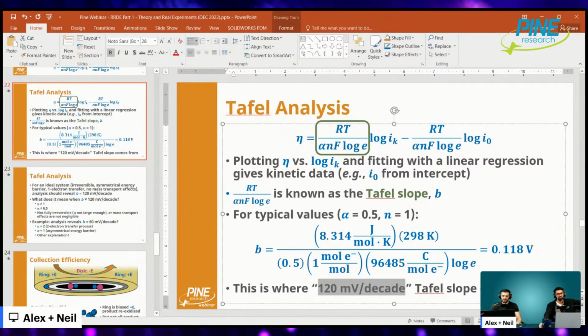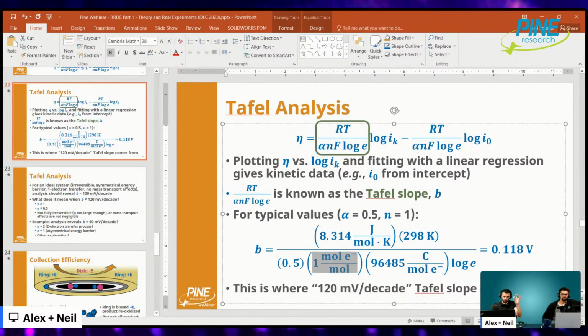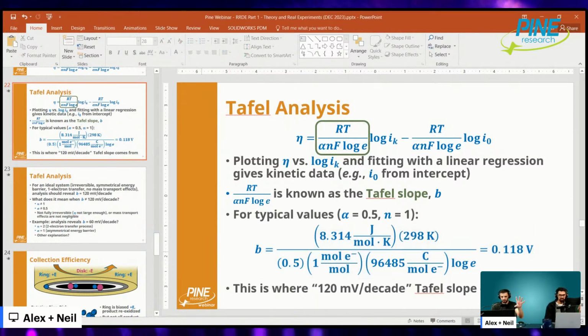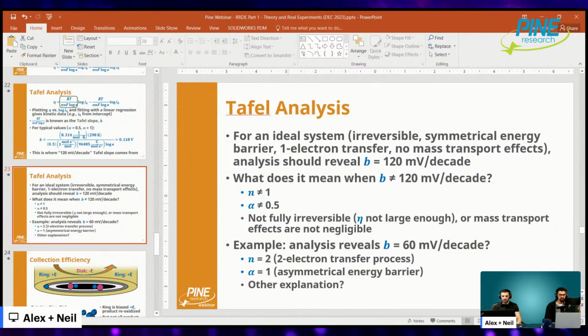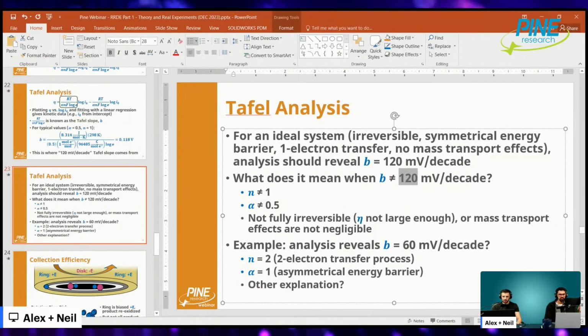So a lot of times what you see as far as what does my Tafel slope mean is it's usually a multiple of 120 or lower. So if it's 120, that means n equals 1. If it's 60, n is 2. If it's 30, n is 4. If it's 40, n is 3. As a side note, that's also a tricky thing because technically speaking, this equation has the assumption that it's a one electron irreversible process. And so we're sort of already disobeying to a certain extent when we have multiple electrons transferred. It's a bit of a catch-22, but I'll leave that there for now. But generally speaking, what you're looking at is somewhere around 120 or lower, usually.